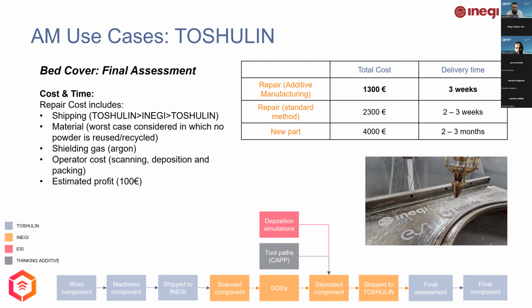The results show that repairing this part with additive manufacturing takes about as long as the standard repair method. However, the costs involved are significantly lower, and since this was the first repair done in these conditions, it is believed that improvements can still be done to lower costs even further.